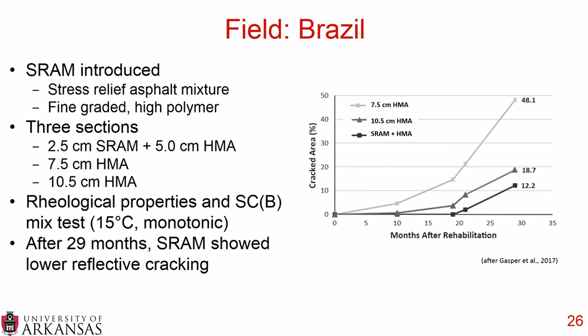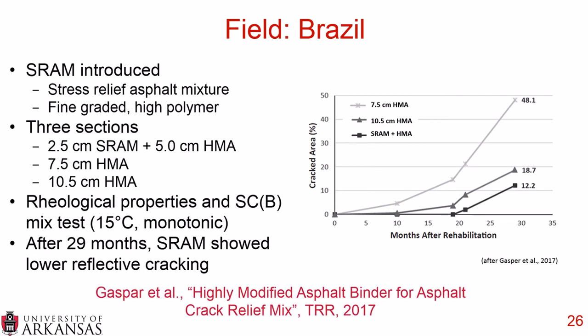So you can see the thinnest HMA layer, the 7.5 centimeter, by far shows the highest percentage of cracked area. It got up to 48.1 after 29 months. Whereas the 10.5 centimeter only had 18.7, and the SRAM plus the HMA only had 12.2. So you can quite easily see the impact of the SRAM and how it does reflective crack a little bit, but it's less, and it's certainly delayed over having just a normal overlay or even a thicker overlay. And you can find much more about this in Gaspar et al. The paper is titled Highly Modified Asphalt Binder for Asphalt Crack Relief Mix, and this is in Transportation Research Record in 2017. So lots of additional reading if you are so interested.